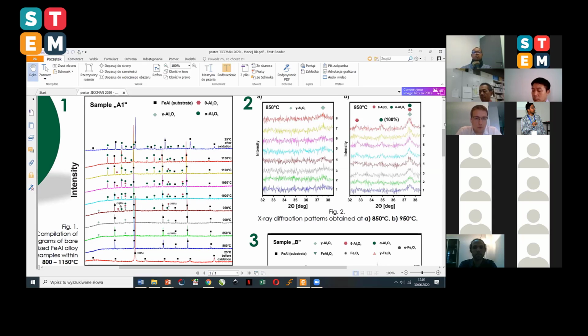And so right now I would like to focus on figure number 1 and the fact that we observed all alumina phase transitions. So starting from 850, we saw the formation of the gamma alumina phase, and on the right side you can see the increasing intensity of the reflection coming from gamma alumina, and then at 950 we observed the formation of theta alumina, so the next metastable phase, and also alpha alumina. And here in picture number 2b, you can see the increasing intensity of the reflection coming from theta alumina and also from the alpha alumina 100% peak. So both gamma to theta and gamma to alpha phase transitions were confirmed.